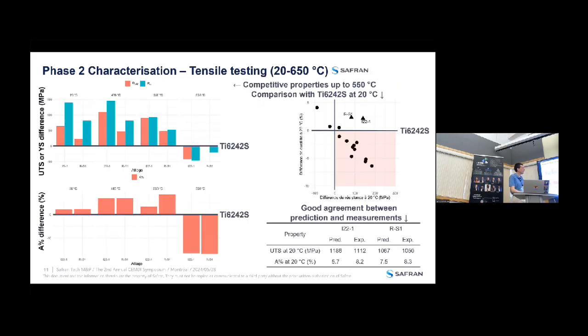The idea there is that we tested these phase 2 alloys the same way, as compared with the phase 1 alloys. And what we found here is approximately the same representation as before. You have the ultimate tensile stress or yield strength difference relative to TI6242S. You can see that it works quite well up to 550 degrees Celsius. Then it all goes down, either in terms of resistance or in terms of ductility. So it doesn't work at all temperatures, not as we wanted. But if you look at the same graph as before, the position of the two phase 2 alloys is actually quite good. I will say it's a bit exaggerated, but we kind of beat the physics there by having alloys that are both more ductile and more resistant. It doesn't work at all temperatures, as I said.